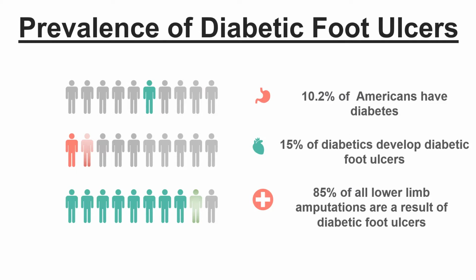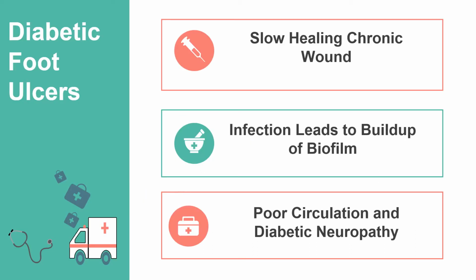Diabetic foot ulcers are a highly prevalent condition that significantly affect the life quality of millions of diabetics. 10.2% of Americans have diabetes, 15% of diabetics develop diabetic foot ulcers, and 85% of all lower limb amputations are a result of diabetic foot ulcers, which shows how common this issue is. Ulcers occur as a result of chronic wounds or high pressure on the foot. Healing is especially difficult for diabetic foot ulcers that are infected and lead to biofilm buildup because diabetics have poor peripheral circulation and neuropathy from increased blood glucose that damages vasculature, and these are the issues that ChitoAid addresses.